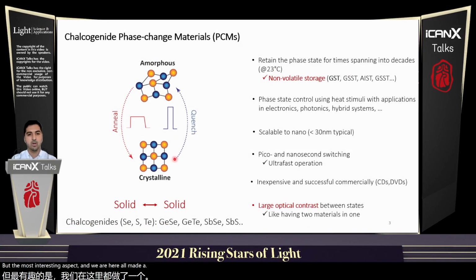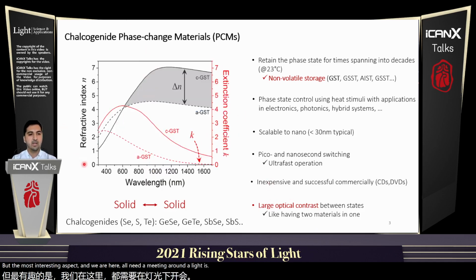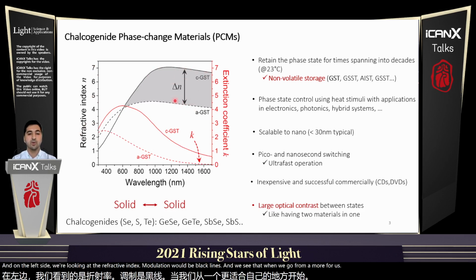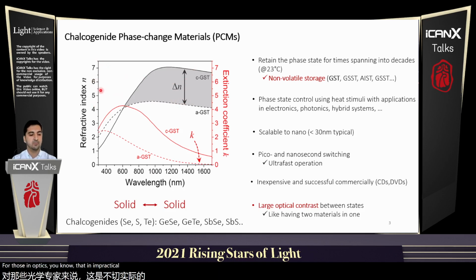But the most interesting aspect, and we are all meeting here around light, is the large optical contrast. And with this, I mean this kind of behavior. We are looking at GST, the most well-known phase change material, and on the left side, we're looking at the refractive index modulation, the black lines, and we see that when we go from amorphous to crystalline state, the change in refractive index is gigantic, right? For those in optics, you know that a refractive index change of 3 is huge, and it's orders of magnitude larger than many of the other effects that we use to modulate light. But simultaneously, we also have a modulation of the extinction coefficient, which accounts for losses.